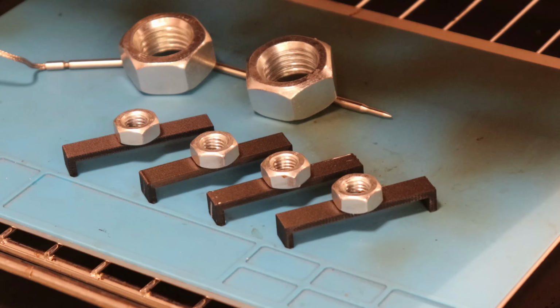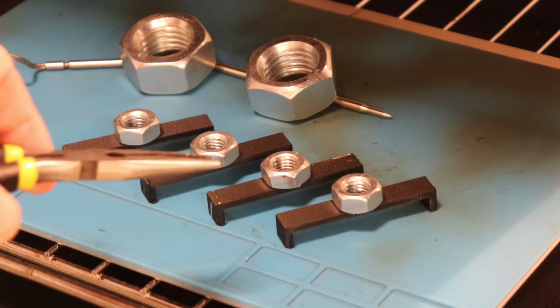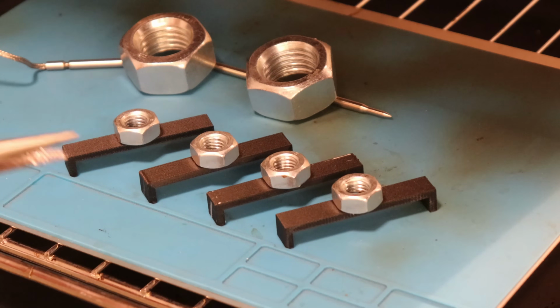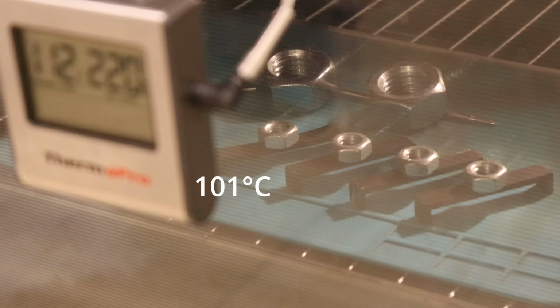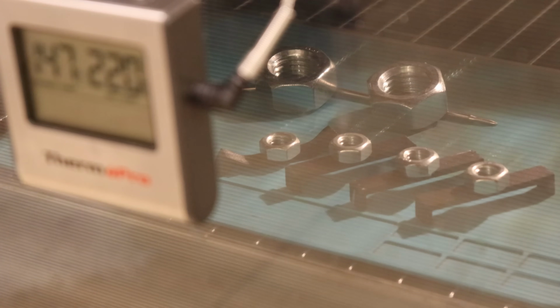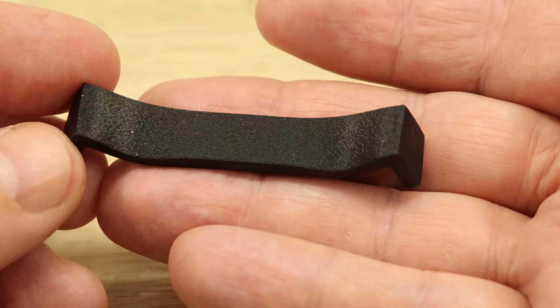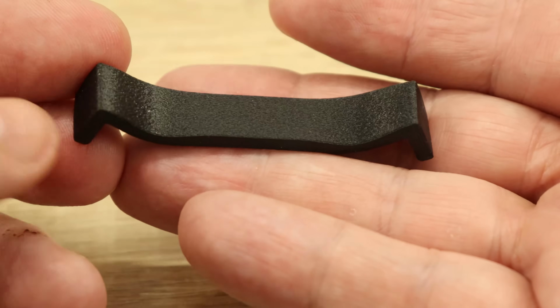Temperature test in the oven, and this is carbon fiber ASA from this test. These are some nylon filaments, completely different category in this kind of testing. This is speed up time-lapse video, and this carbon fiber ASA started to deform on a little bit higher temperature compared to the regular ASA. It started to deform at 101 degrees Celsius, and on 150 I stopped the experiment. The surface quality is nice, but of course it is deformed a lot.